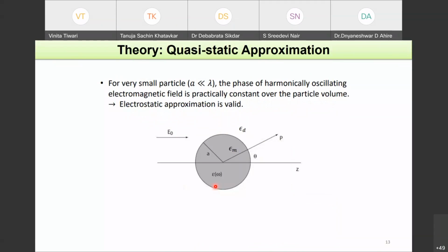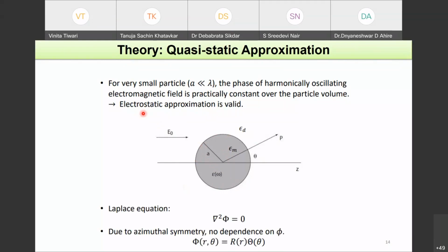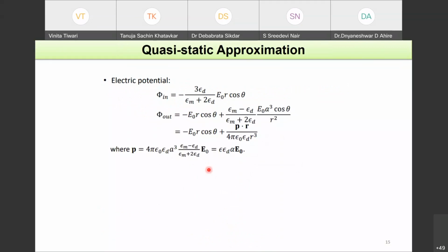Now, how do we describe these nanoparticles? There is a very standard and easy theory that can handle these nanoparticles. I'll not go into much detail, I'll just show you that a very simple theory can handle these nanoparticles. If your nanoparticles are much smaller than the wavelength of the light that you are working with, you can assume that the electromagnetic field is basically constant over the particle volume. So in that case, you can assume that the electrostatic approximation is valid. Okay, so you can simply solve the Laplace equation and obtain the potential inside and outside the nanoparticle.